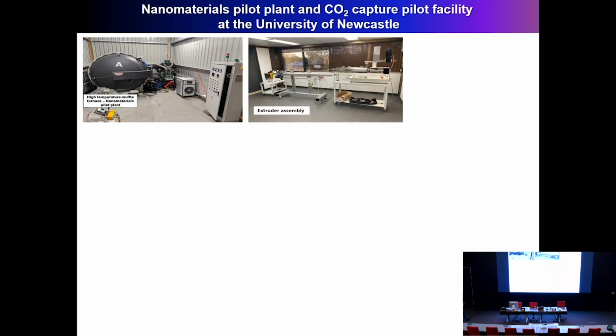So, not only the basic research, but we also translate that basic research into real commercial products. In our center, we made a bulk production facility for the nanoporous carbon nitride or carbon material, and we made hundreds of kilograms of the material, and we now engaged a partnership with an Indian company to produce 40 tons of the CO2 per month, right? Sorry, 40 tons of the materials per month, right?